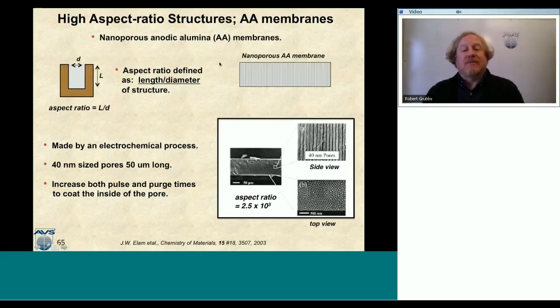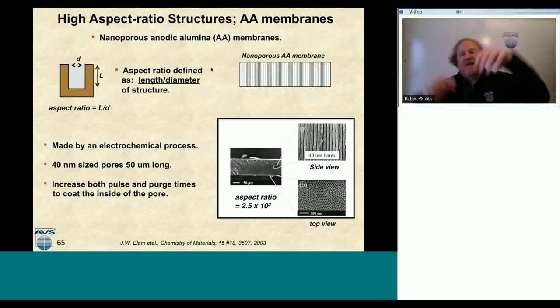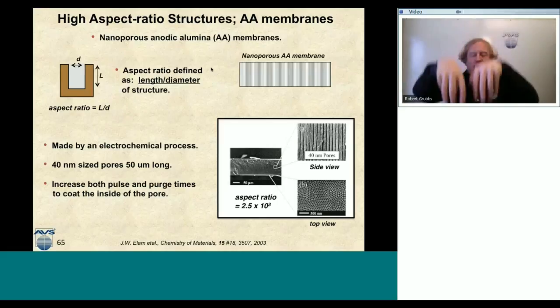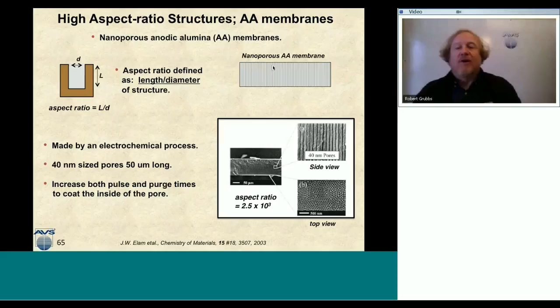So one interesting experiment was performed on this nanoporous anodic aluminum membrane. This is like a piece of aluminum foil, and you put a particular voltage on it and use this electrochemical process, and you can actually etch pores right through your membrane. In this picture on the right, there's the side view showing the pores. You can see that they're 40 nanometer pores. They're very, very small. They're 400 angstroms wide.